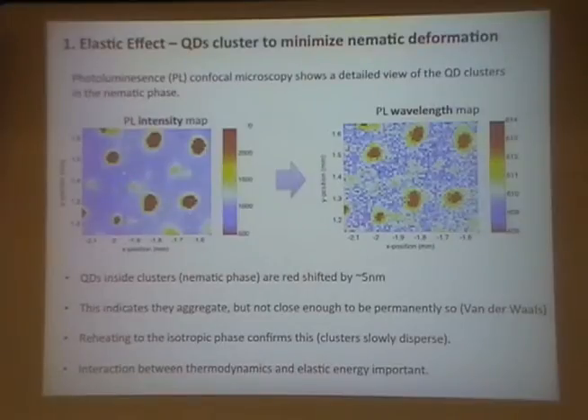But there is quite a bit in the background as well. These are ones that are low down, so they're slightly out of focus. That's why they look different. These ones are in the middle of the confocal plane. Now if you look at this map, we can see the wavelength map that goes with it, because each pixel on this image can give us a spectrum. This map shows the peak of the emission of the quantum dots, and we can see something interesting. At first it looks like they're the same, but because this is a wavelength map, not intensity, we can see in the center of the cluster there is a lot of redshift. This is now a lookup table for wavelength, not intensity. So in the center of the cluster, it's really redshifted.